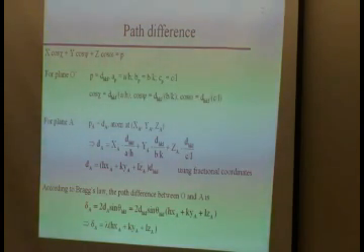And what we know from Bragg's law is that the path difference is 2d sine theta, right? In this case, our distance happens to be dA, right? Now remember, we are still looking at the same diffraction direction, so it's still sine theta HKL. So our delta A, our path difference for that atom A, is equal to 2d sine theta HKL.